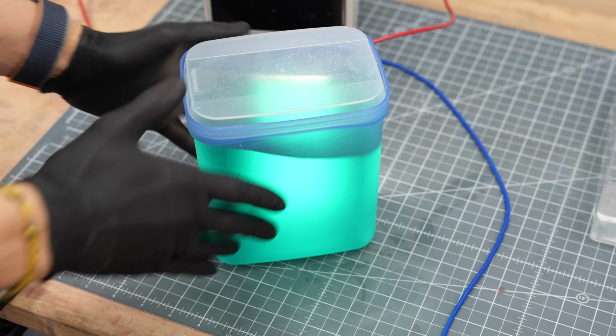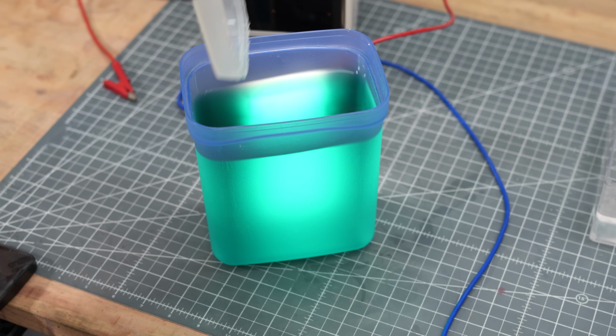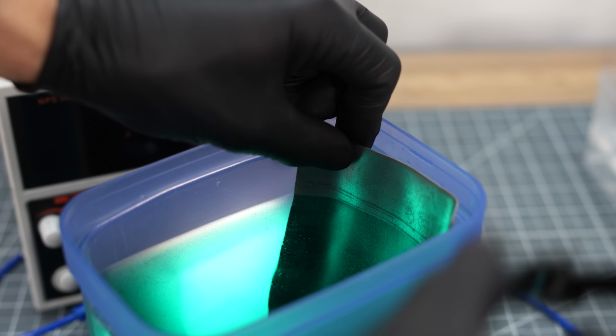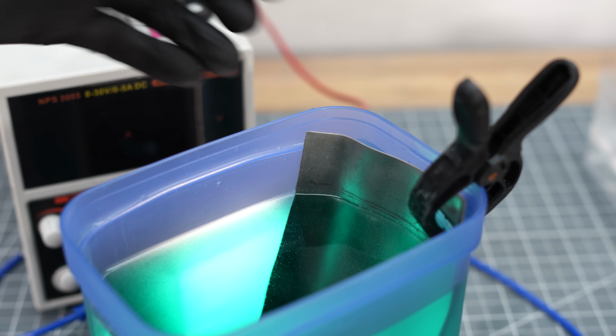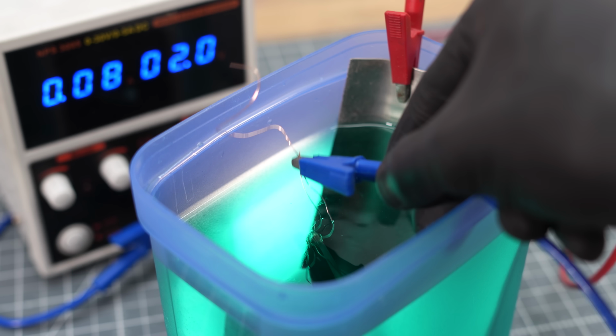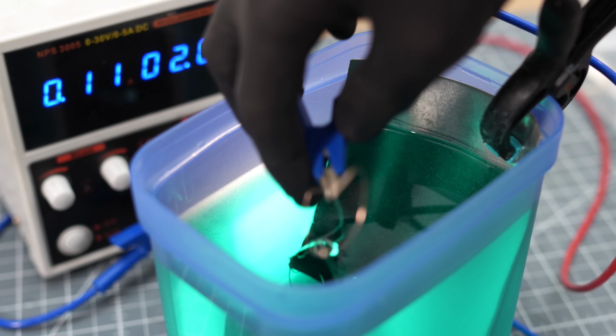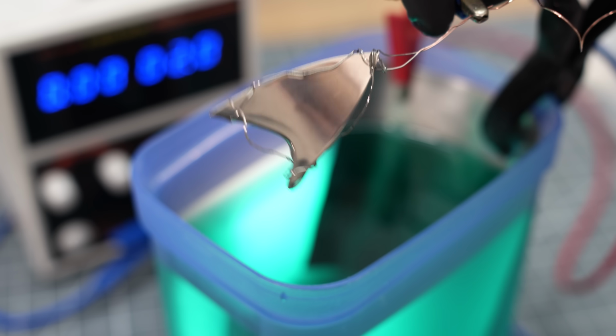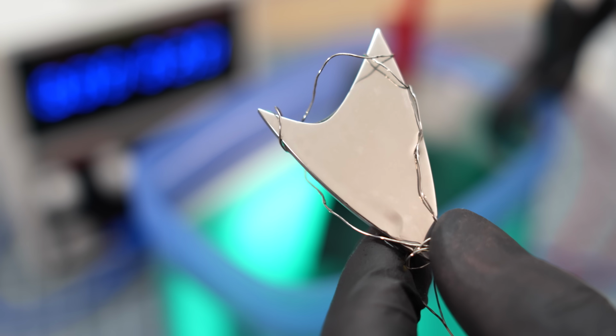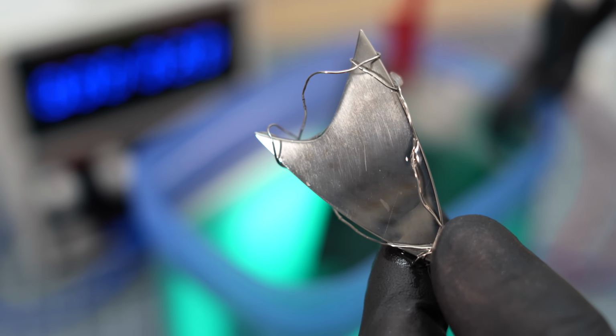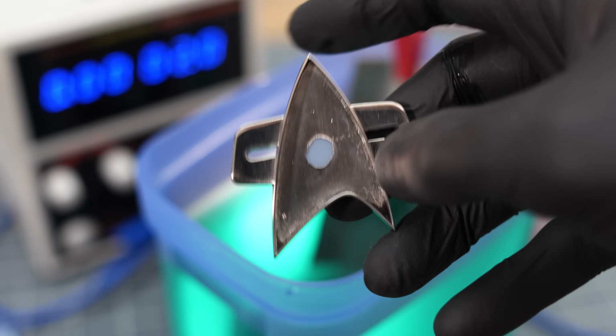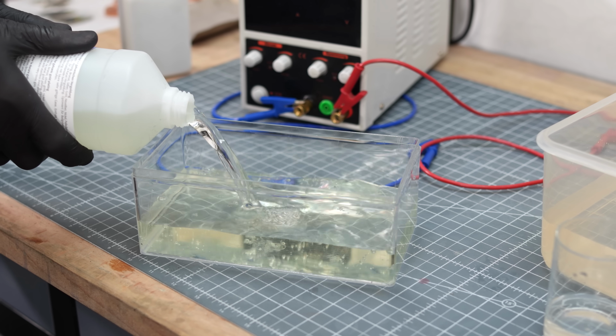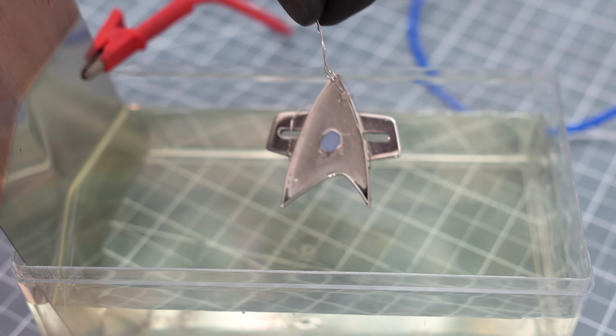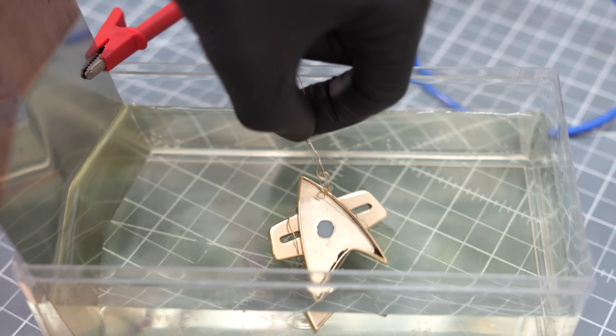Now nickel and gold are applied to the parts. Here too, I use a bath. Although it's not absolutely necessary, only very thin decorative layers are deposited, very briefly. This can also be done with a galvanic pen. Nickel works without issues, 3 minutes at approximately 2 volts. The gold electrolyte also presents no problems, the parts stay in it for only 20 seconds as it's otherwise too expensive.